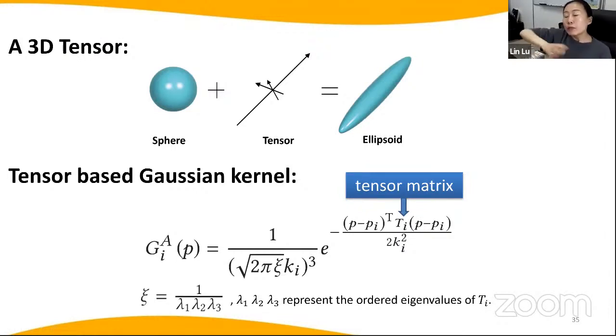So if we want to represent the pore, and also with directions, a 3D tensor is a good choice for representing the pore shape. It's like this figure: a 3D tensor has three orthogonal principal directions, and if we apply it to a sphere, we get an ellipsoidal shape. Then we propose the tensor-based Gaussian kernel. That is, we use T_i, the tensor matrix, in the distance matrix, such that we can get a directional Gaussian kernel. This is not new, but it hasn't been used to model pores.